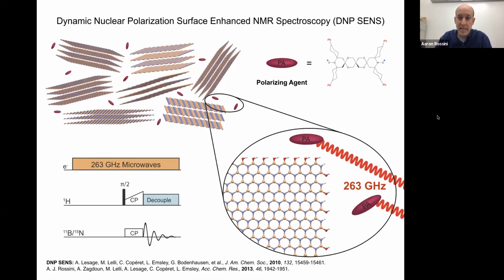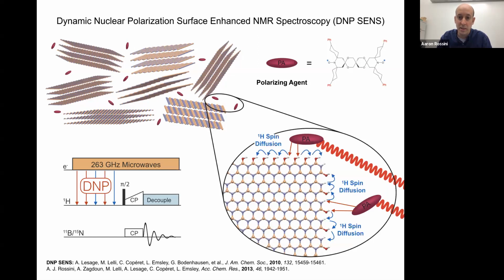When we do DNP, we're going to irradiate our polarizing agent with microwaves. That's going to cause polarization transfer to some proton spins that are nearby to the radicals. And then proton spin diffusion will mix that proton polarization evenly throughout the sample. So that's going to polarize both the proton spins of the solvent and the edges. And then we can do a cross-polarization transfer to selectively observe the nuclear spins associated with the edge or surface of the material.